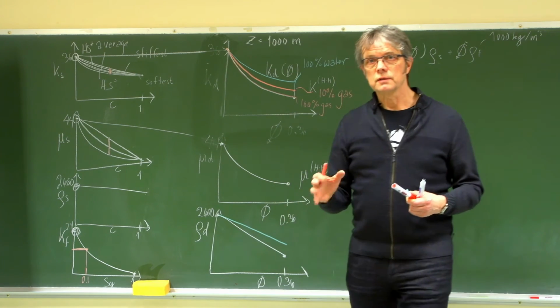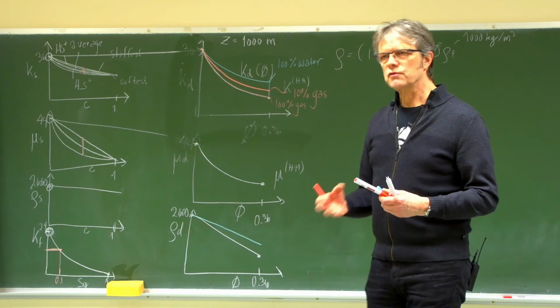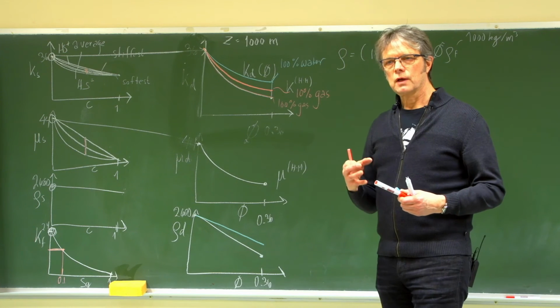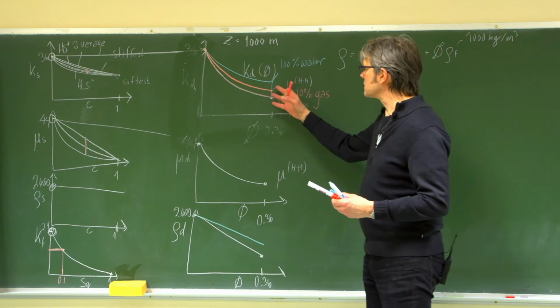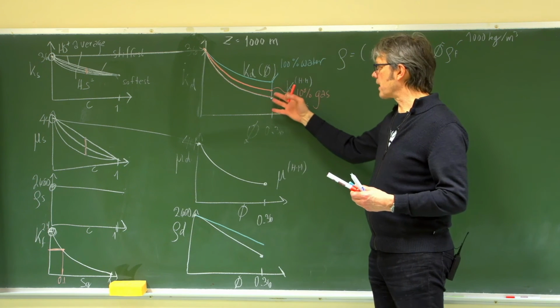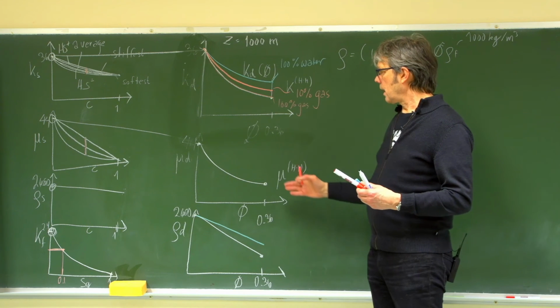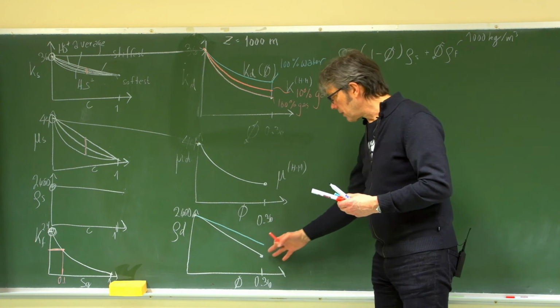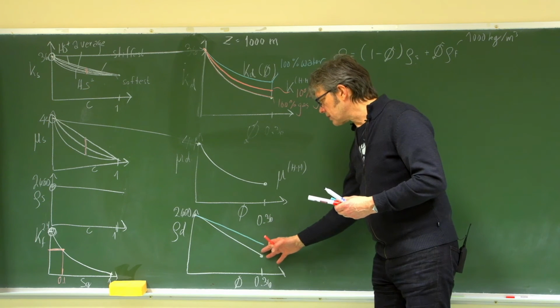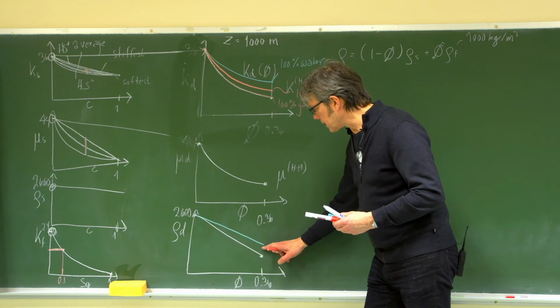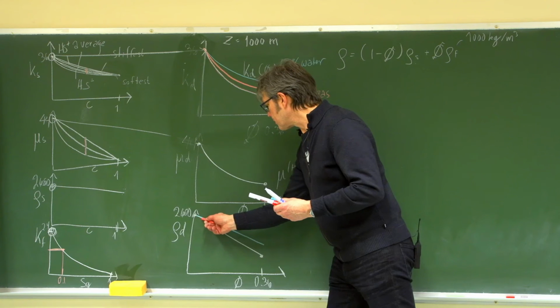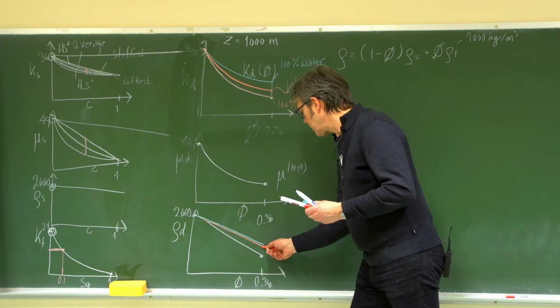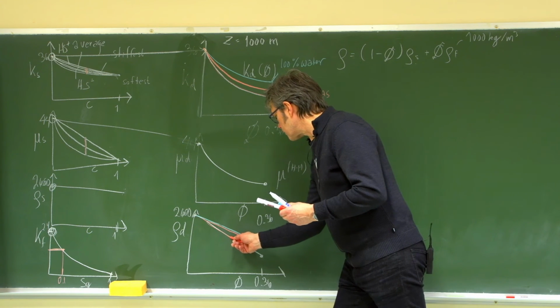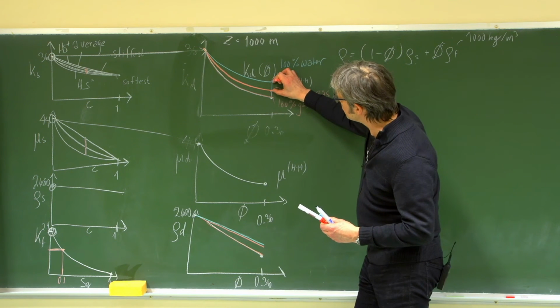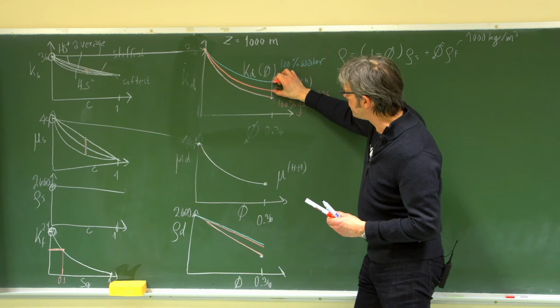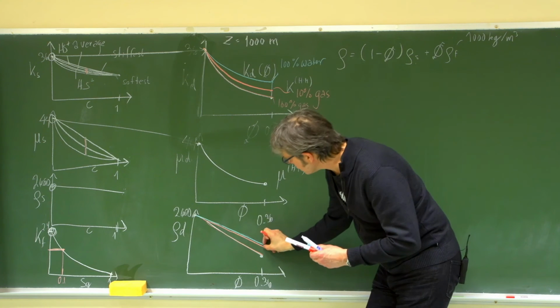And that's why seismic is kind of a bit difficult in reservoir monitoring. In the last stage of the injection process, when the gas content exceeds a certain number, there's very small effects on the bulk, and even less on the shear. But of course, the effect of the gas separation is linear when it comes to the density here. So it would go in equal steps here. So 10% gas would be about here, or 100% gas would be a bit larger than the dry. So we'd have a different jump in the bulk with small parts of gas here and very small here.